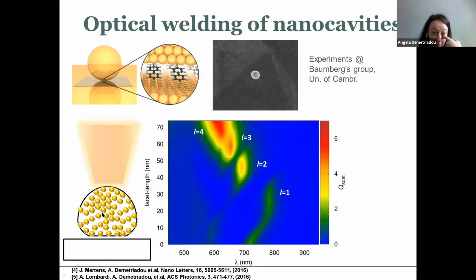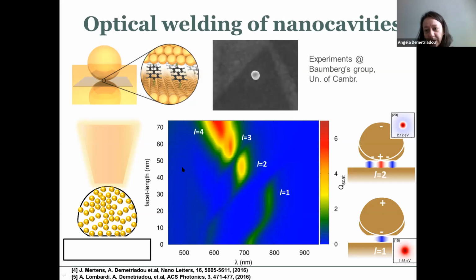And when we were doing those calculations and those experiments, we were observing very peculiar behavior. This is the scattering cross section, and what we would see is that as this gets larger and larger, you start seeing higher order modes emitting very efficiently, while lower order modes become dark, which is something very unexpected. At the time, we were thinking that these modes were switching off while the second order modes were switching on. Somehow something is going on there.